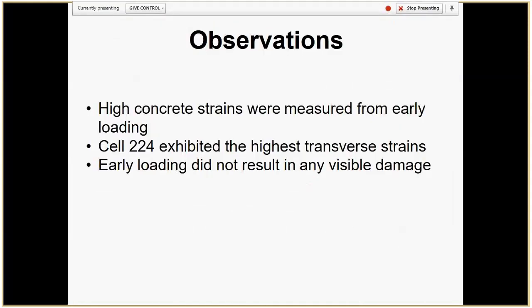But basically our conclusion was that very high concrete strains were measured, and here we even excluded questionable data that might have much higher strains, but those strains did not lead to significant damage, and the explanation is that stiffness was reasonably low and tensile strength was quite high. So basically, if a criterion should be used for the opening, it shouldn't be compressive strength, it should be tensile strength. And if compressive strength is used, it's only a way to estimate tensile strength.